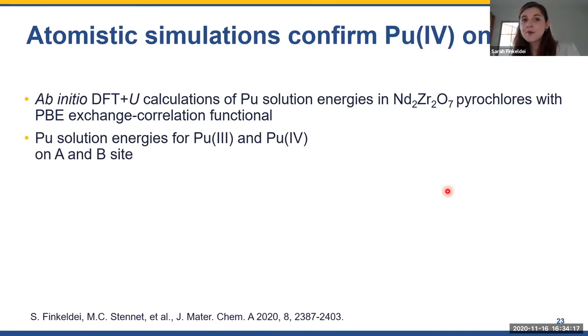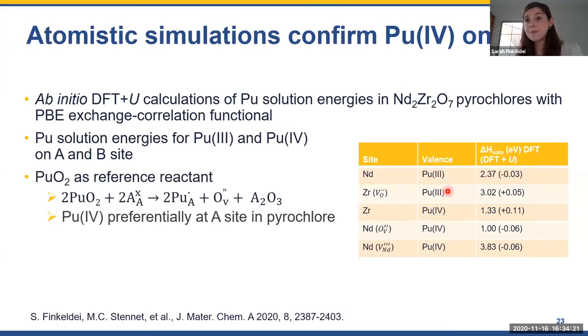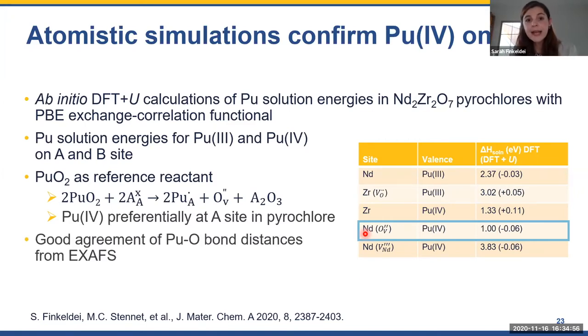What we did is we derived those for plutonium 3 and plutonium 4 on the A and B site to have a very holistic idea about all the solution energies and all the possible scenarios where plutonium could be uptaken. And we took plutonium oxide as the reference state for our reactants, and we found that the lowest solution energy was obtained for plutonium-4 at the neodymium site. Due to the different oxidation states of neodymium and plutonium, we need to balance this via the introduction of oxygen vacancies. And the bond distances for plutonium and oxygen were in very good agreement with the computationally derived ones. So that gave us confirmation of our experimentally derived data.